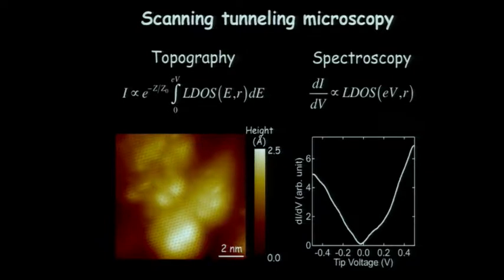We change the voltage between the tip and the sample, and that allows us to tunnel into different states in the sample. These are plots here of dI/dV. This is going to be proportional to the density of states as a function of energy or tip voltage. What you see here is a typical dI/dV curve for graphene. We have this linear dispersion here that's coming from the Dirac cones being linear in momentum. So we're getting dI/dV information which is proportional to the density of states in the sample. So we have these two modes, a topographic mode and a spectroscopic mode.